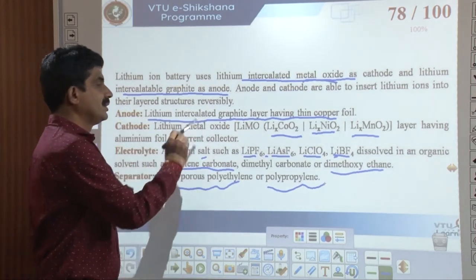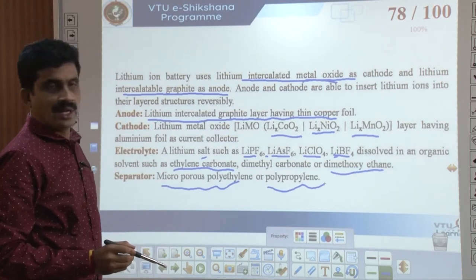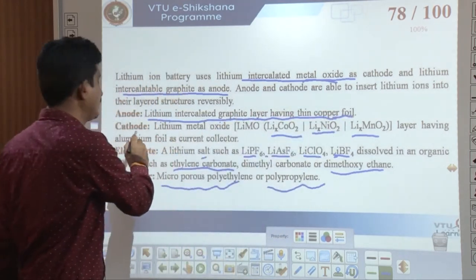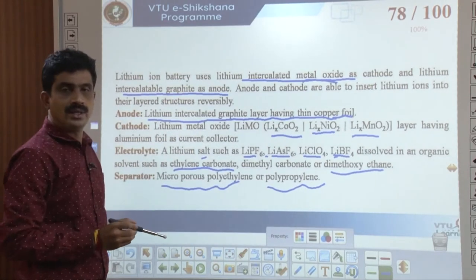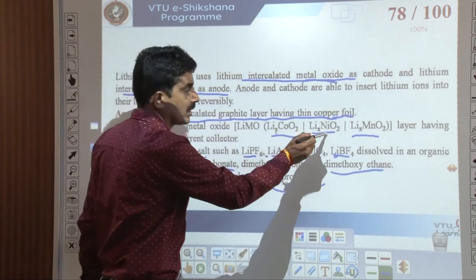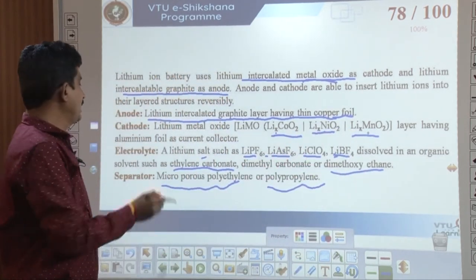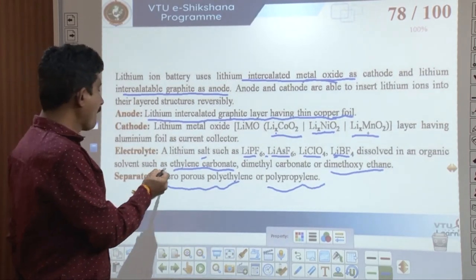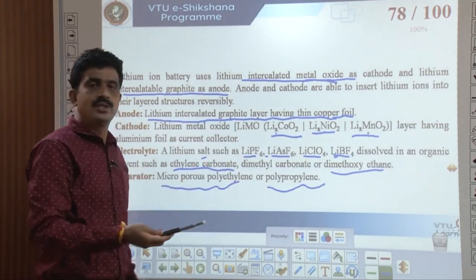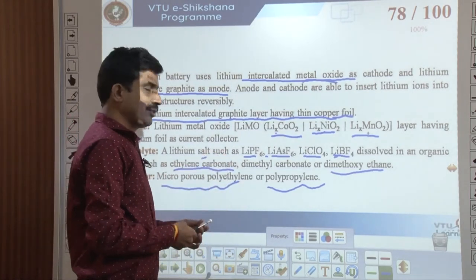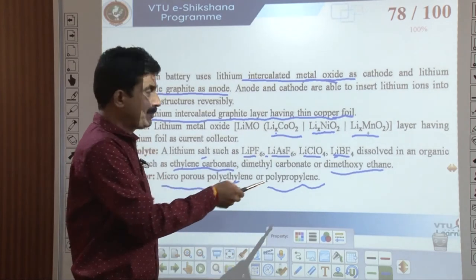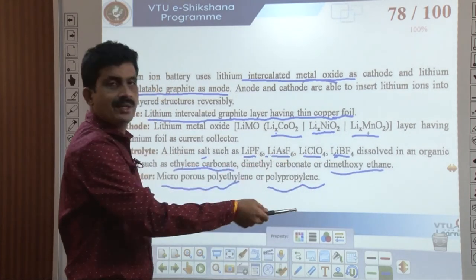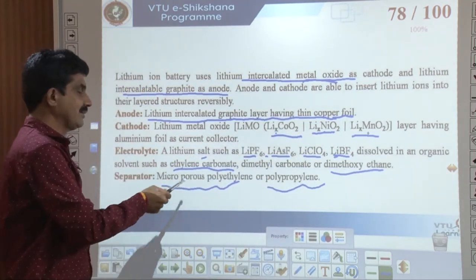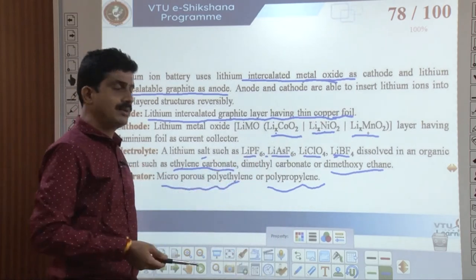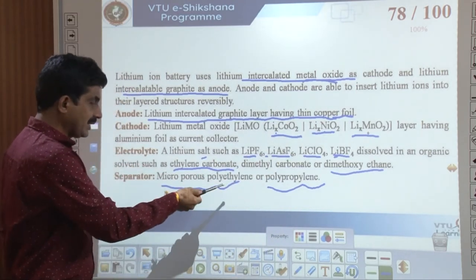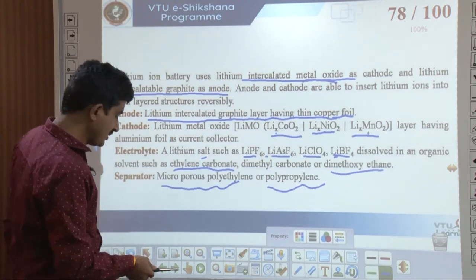So the anode is graphite intercalated with lithium, having a thin copper foil as the current collector. And the cathode is lithium metal oxide such as lithium cobalt oxide, lithium nickel oxide, lithium manganese oxide, having aluminium foil as the current collector. And the electrolyte should be a lithium salt such as lithium hexafluoroarsenate, lithium hexafluorophosphate, lithium tetrafluoroborate, lithium perchlorate, dissolved in an organic solvent such as ethylene carbonate, dimethyl carbonate, or dimethoxyethane. And a polymeric material such as polyethylene or polypropylene is used as the separator.